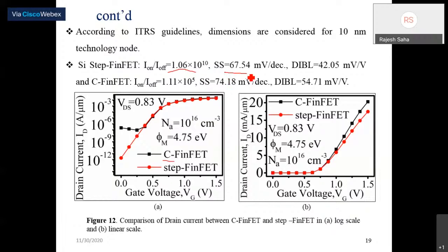Similarly, subthreshold swing we got is 67.54 millivolt per decade, and drain induced barrier lowering we got is 42.05 millivolt per volt. Whereas in the case of the conventional FinFET, the current ratio or switching ratio we got is in the order of 10^5, SS we got is 74.18 millivolt per decade, and DIBL we got is 54.71 millivolt per volt. That means our step FinFET shows better electrical characteristics compared to the conventional FinFET.